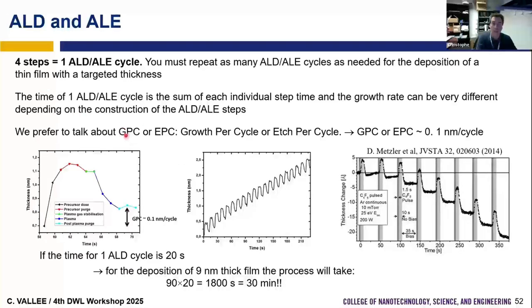And for ALD, we try to understand how much growth we do with one cycle. The sum of the 4 steps is what we call growth per cycle. And usually it's about 1 angstrom per cycle, 1 monolayer. And every cycle you will add 1 angstrom. So you control the growth by the number of cycles. And for ALE, we try to remove 1 monolayer per cycle. So we try to estimate how much we etch per cycle. This is what we call EPC. And for example, the same order of magnitude could be 1 angstrom per cycle. And you can see the same ALE process where we try to remove 1 monolayer per cycle.